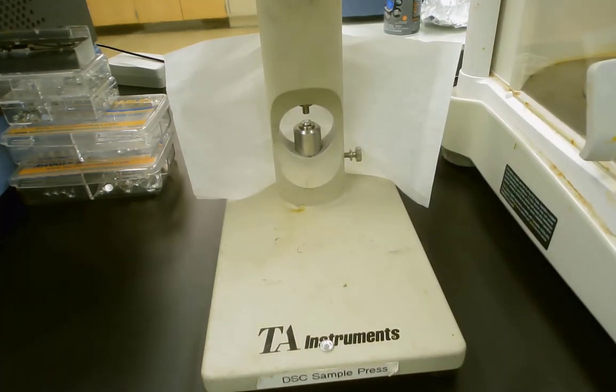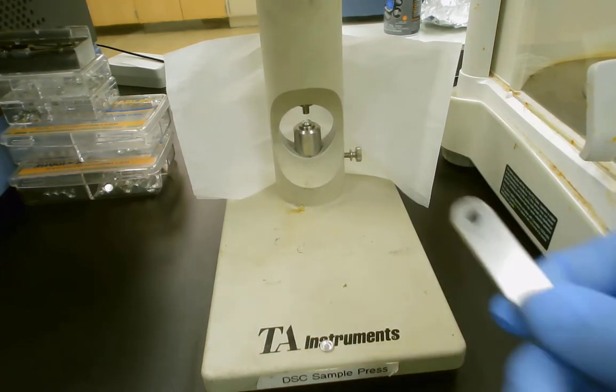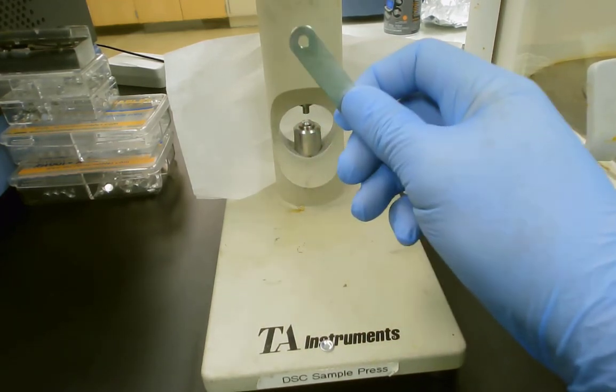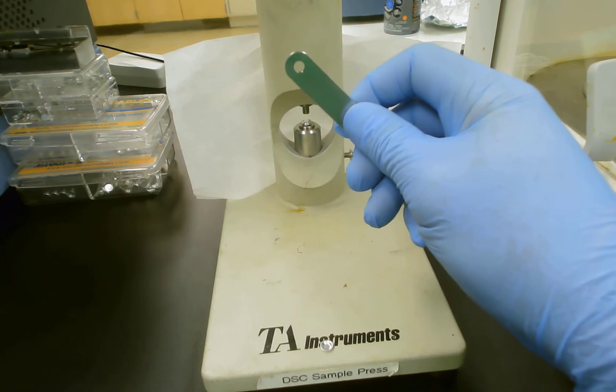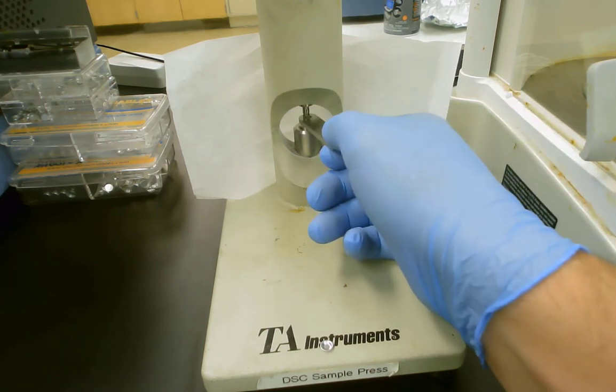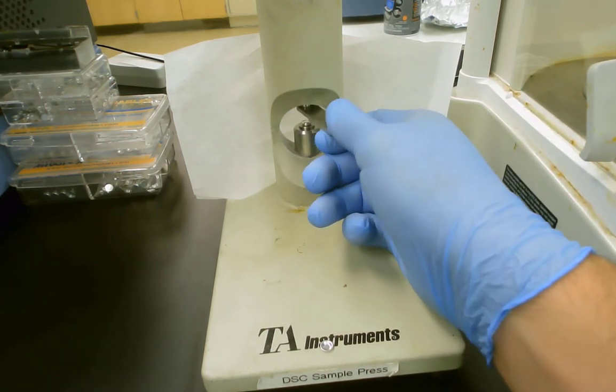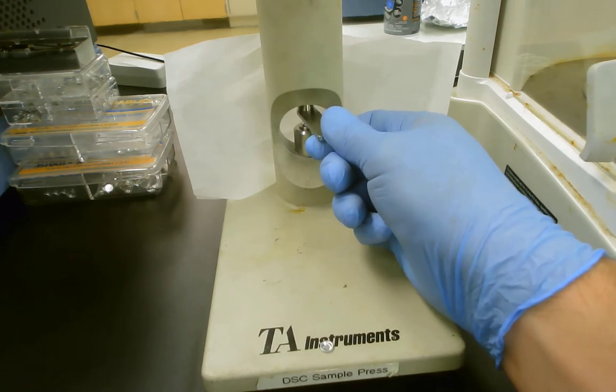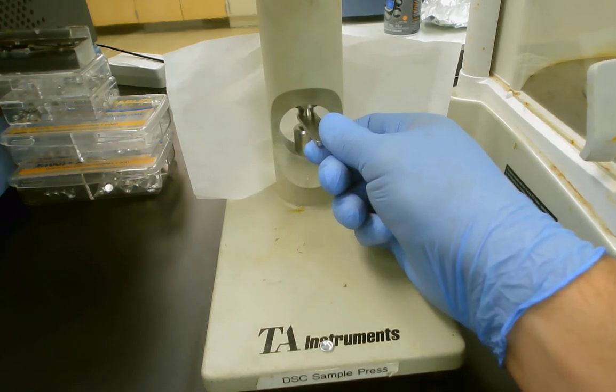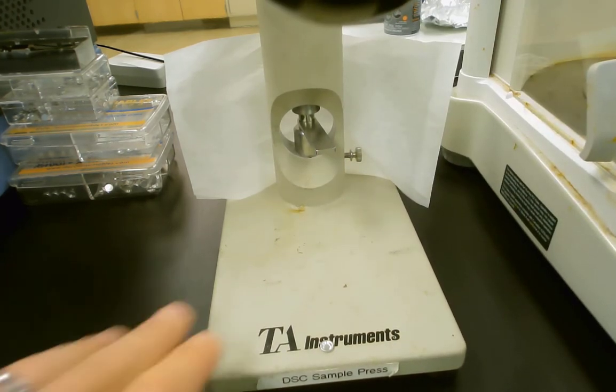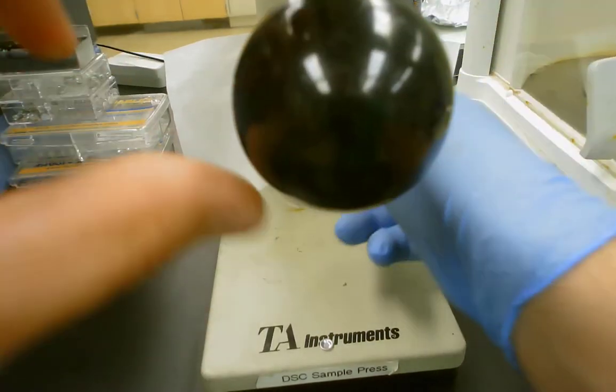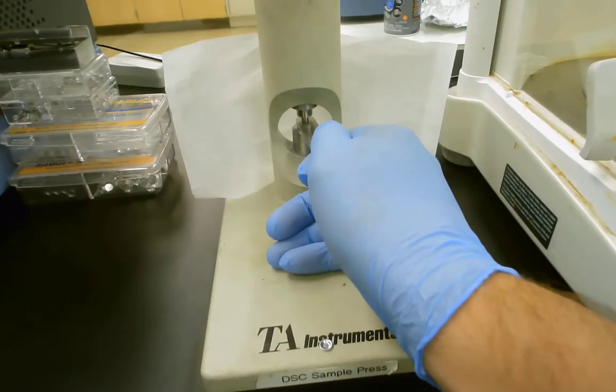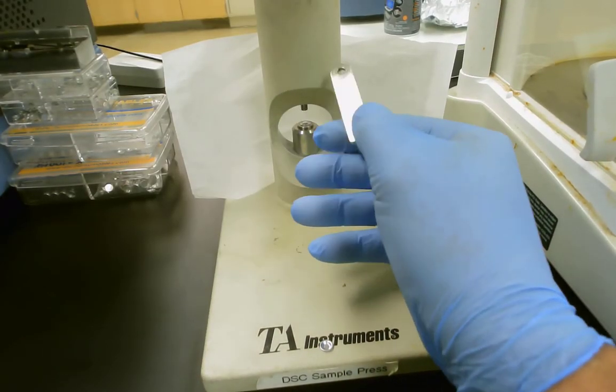There we go, contrast. So the little pin comes down and is the same size as the hole in our die. So first we're going to do the beveled side down. That's going to take the pan edges and bend them in just a bit. And so all we do is then push down on the handle, which is super in front of the camera. And then you don't have to push very hard. This is very thin aluminum.